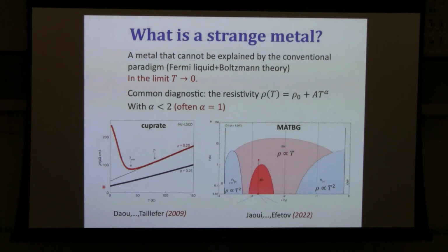There are other more recent examples. For instance, this is magic angle twisted bilayer graphene, where recently it's been reported that over a broad range of electron densities or fillings, the resistivity of the system is linear in temperature, and this extends down to a few tens of millikelvin, which is a very, very low temperature for this system.